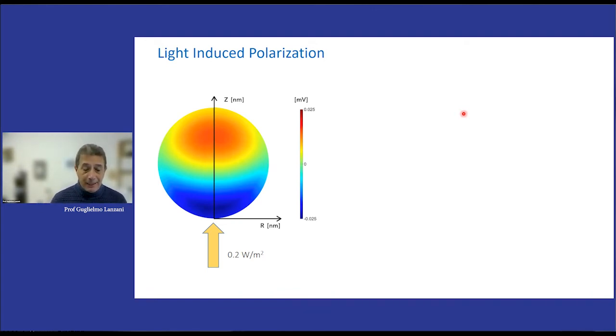Note that at the beginning, I thought I was discovering a new phenomenon, this light-induced polarization. But then it turns out that it's not new. So Dember was already talking about this phenomenon in the 1930s. So it's a well-known phenomenon occurring at the semiconductor interfaces. You see here what happens when you shine light from the bottom, for instance, in a nanoparticle. And there is a profile which is bending a bit in this direction, as you see very well here.